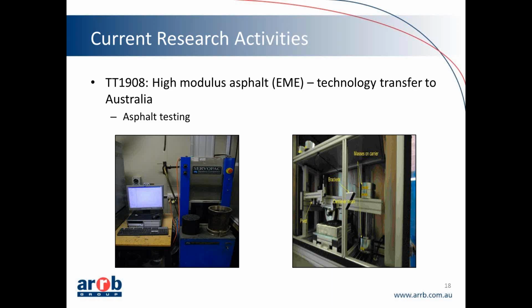The temperature was 60 degrees, but the main thing that was different for the EME mixes is that they were actually compacted at quite a lot lower air voids than what we would typically see. So the Austroads test method for wheel tracking specifies that we need to test to 5% air voids plus or minus 1%. And what we did for the EMEs is we were at roughly 2% air voids from memory, which is quite low. So that's the main variation that we did for the wheel tracker, was that the air voids that we had to target was quite a bit lower, and that matches up with the EME technology in France as well.